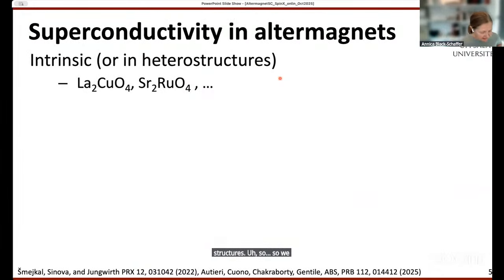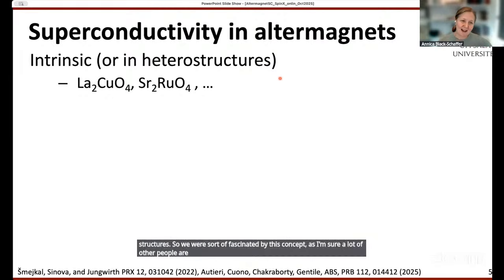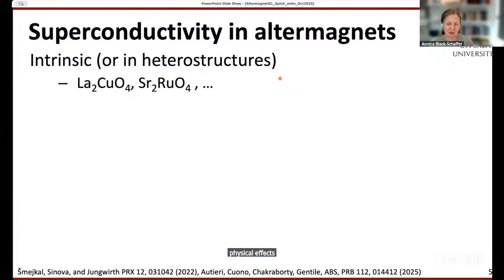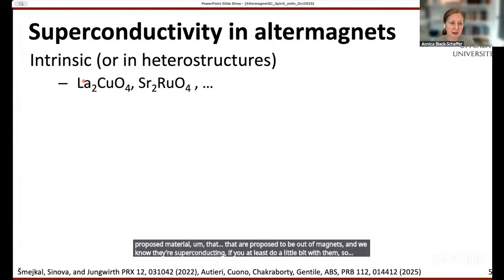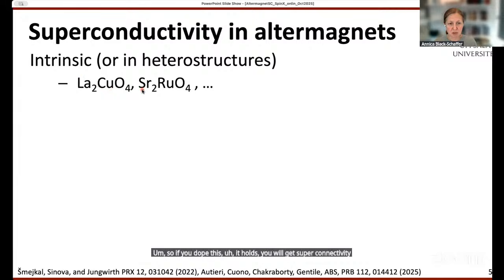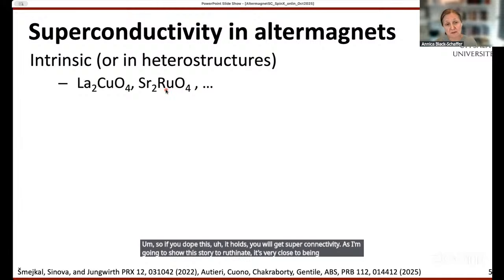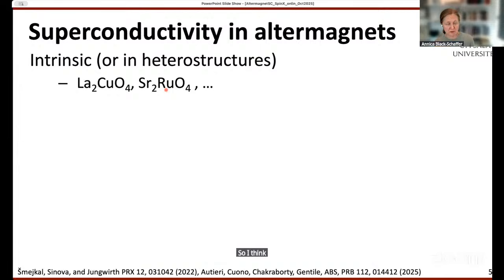So we were fascinated by this concept, as I'm sure a lot of other people are as well. And we were thinking, okay, so with our background in superconductivity, what would that mean for superconductivity? And of course, you shouldn't just think about combining different physical effects if there's no chance of finding it in nature. But there are some materials that are proposed to be altermagnets, and we know they're superconducting if you at least do a little bit with them. So lanthanum copper oxide is proposed to be an altermagnet, and it is a parent compound of a cuprate. So if you dope this with holes, you will get superconductivity. As I'm going to show, strontium ruthenate is very close to being an altermagnet, we think, and that is an intrinsic superconductor.